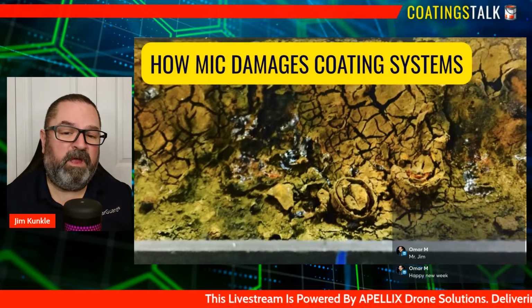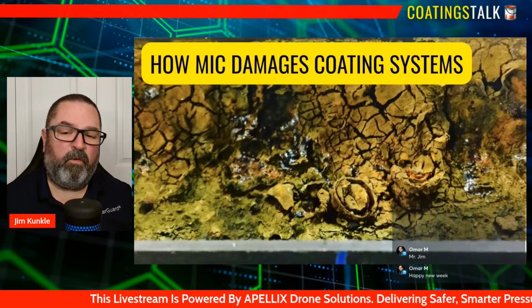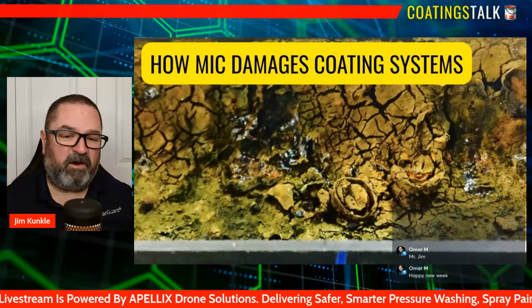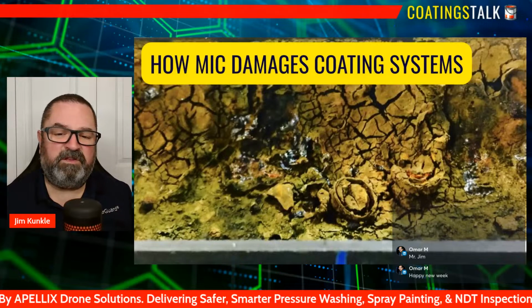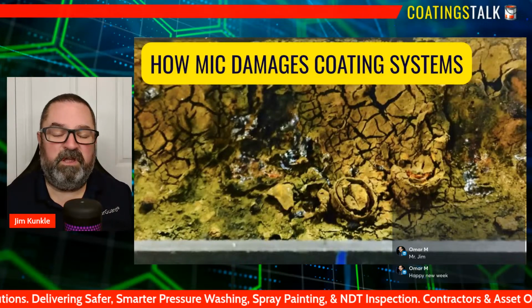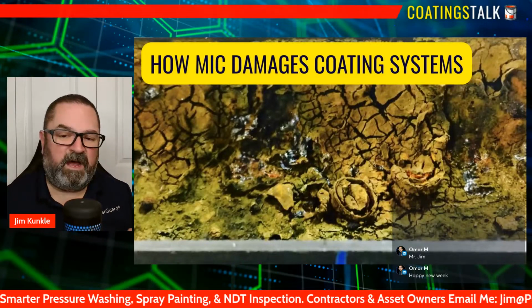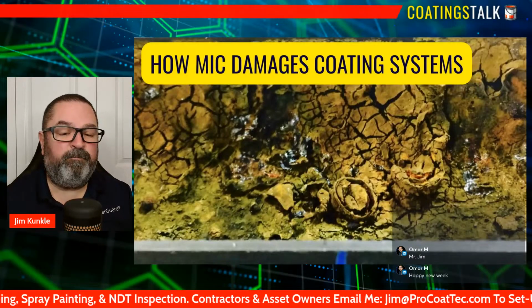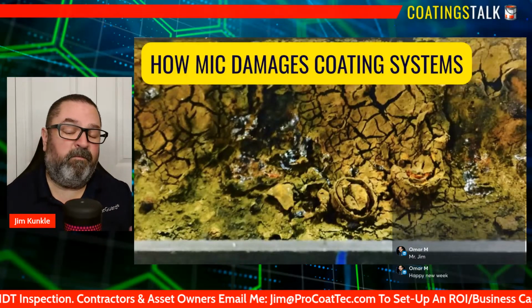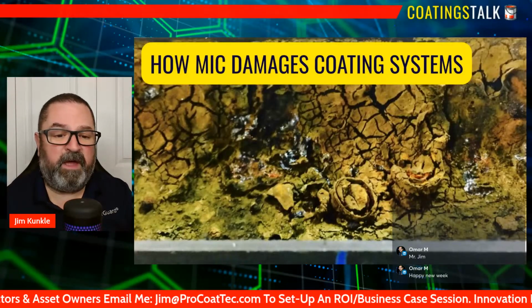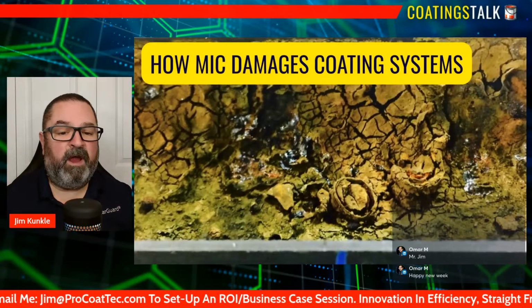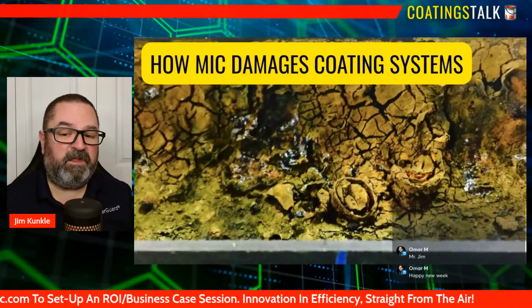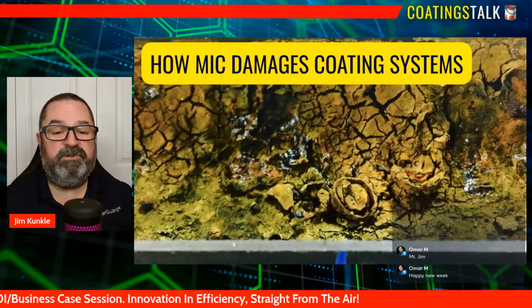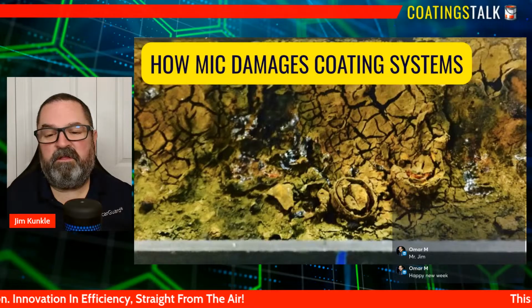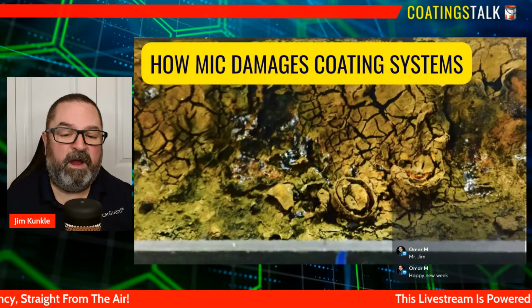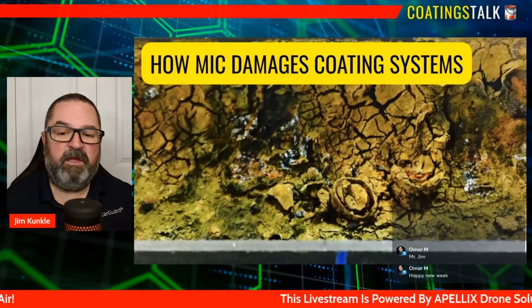Microbial colonies can create differential aeration cells where oxygen levels vary drastically across tiny distances. And these oxygen gradients accelerate localized corrosion, which often results in deep pitting directly under the coating. In some cases, sulfate reducing or acid producing bacteria can chemically degrade the coating resin itself, which weakens adhesion and allows underfilm corrosion to spread rapidly. The result is a failure pattern that looks like premature coating breakdown, blistering, undercutting, or delamination.